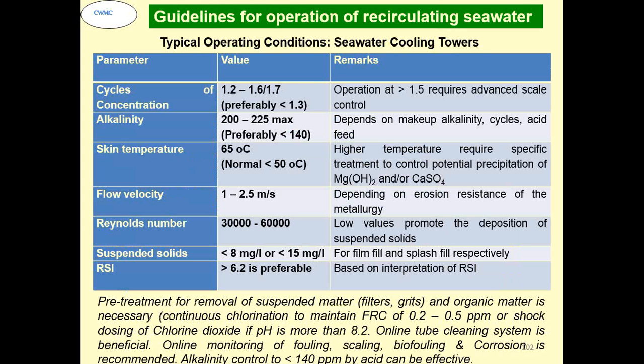See, this is the tentative guideline that we had developed for operating with a seawater system. Cycle of concentration 1.2 to 1.6, maximum 1.7, preferably less than 1.3 if we are not dosing anything. If you are going beyond that, that means we have to do the chemical treatment of the seawater also. Alkalinity should be maximum 225. Skin temperature not more than 65 degrees. Below 50 degrees is normally the acceptable range.